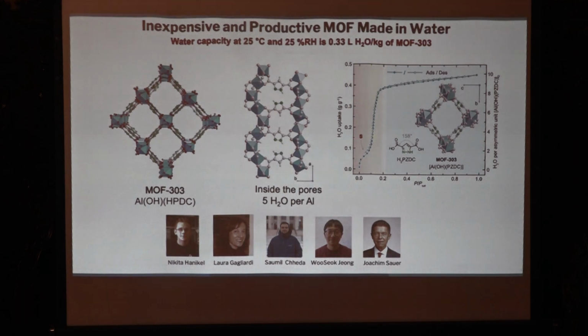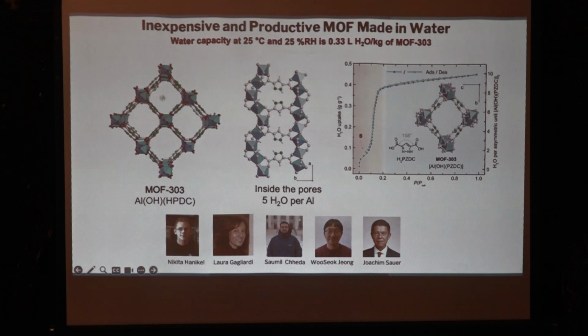So, long story short, I'll give you the answer now. We created a MOF. We call it MOF-303. It's an aluminum MOF, and it has these rectangular pores. If you are a molecule of water floating in the pore and you're looking around the walls of the material, you'll see hydrophilic sites. These are NH and N. This is pyrazolate. Hydrophilic and hydrophobic, hydrophilic, hydrophobic. Avogadro's number worth of these in a mole of this material.